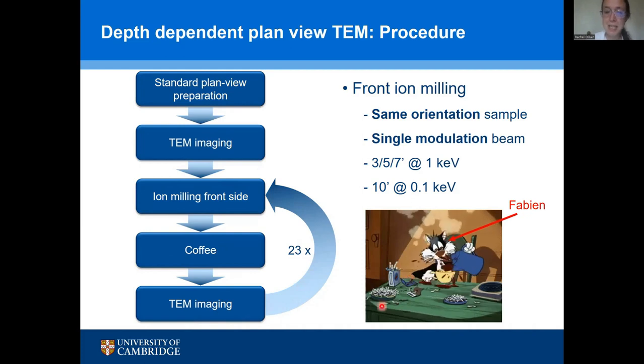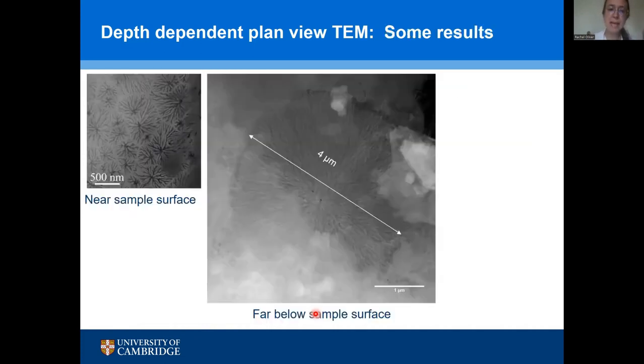Fabien reckons this is him during this experiment, because we had the microscope available basically for a 24-hour period and kept going round and round the cycle. And it was very hard work. And then he eventually went home to bed and had a good long rest thereafter. But what that allowed us to do, and I'm not going to talk about all the many layers we see, is sample the layers both near the sample surface and very deep below the sample surface.